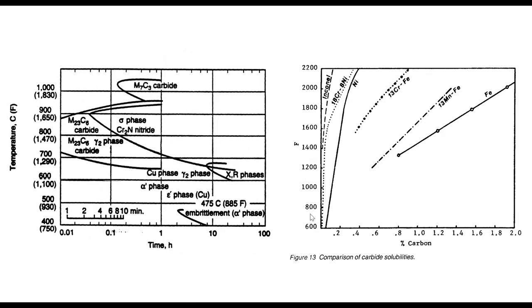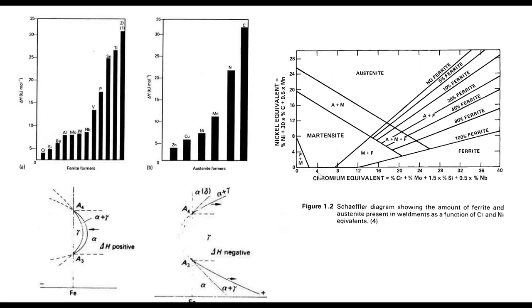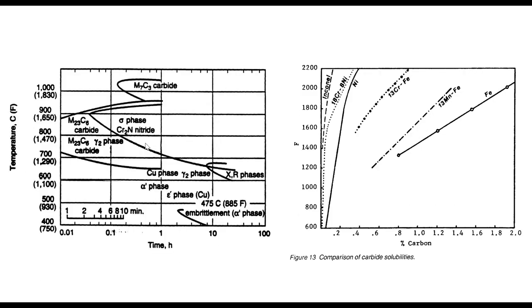The challenge I have with heat treating the stainless steel is that I have to get rid of all these nasty things that happen just like pearlite forms or carbides form in ordinary alloy steels. Even with 0.03 or 0.04 carbon, I still get carbides. I also get another phase that's chrome nitride and then I get sigma phase, which is really brittle. This is sigma phase. I really have to worry about what happens. I can even get embrittlement here at longer times. So in normal heat treatment or casting, I form all of these nasty things.